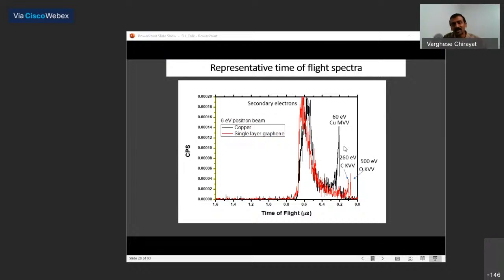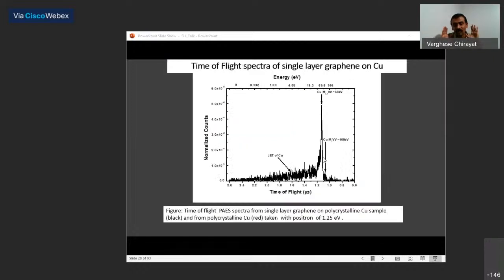Now, what I do is, instead of using 6 eV positrons, I use 1.25 eV positrons. 1.25 is much lower than the work function for single layer graphene or even copper. Both of them are around the work function. The energy required to remove the electron is around 4.5 to 5 eV, much smaller than that. So there is no secondary electron emission. So boom, your low energy secondary electron background is gone.